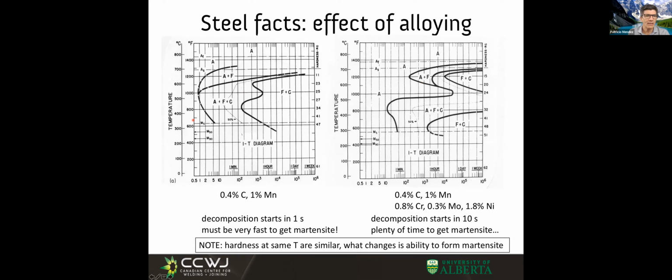And what we see here is that if we do our very artificial heat treatment of doing a quench and holding at a temperature, we would get primary ferrite. We hold it and eventually it turns into pearlite. And if we do this hold at lower temperatures, we go straight from austenite into the final product, that is bainite.